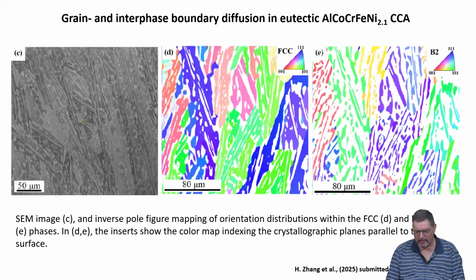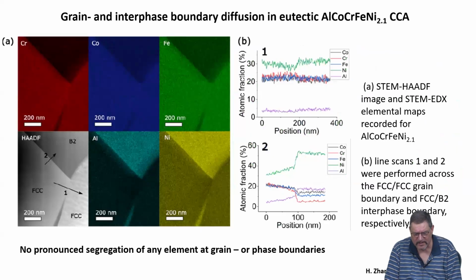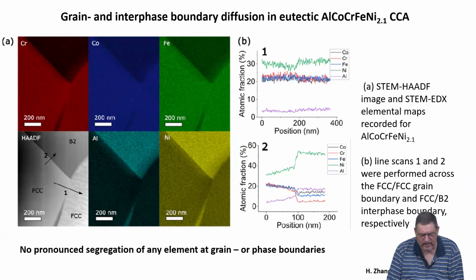This is how it looks like. Very nice eutectic microstructure in the SEM. And basically, you can see the orientation distribution of both phases, FCC and the BCC, the B2 phase. So only two phases present. Concerning chemical distribution, this is also nice because we can see that we have rather uniform chemistry.